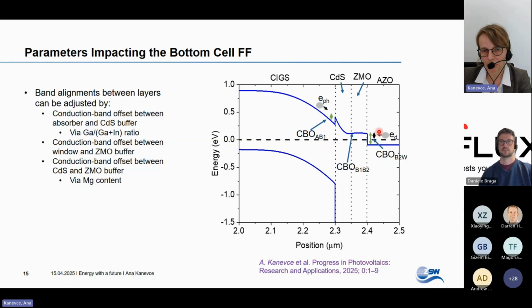So the conduction band offset can be varied. For example, zinc magnesium oxide band gap can be varied with magnesium versus zinc ratio. CIGS band gap, as said, can be varied with gallium versus indium. This is a little bit problematic because if we want to use CIGS as a bottom cell, we want to reduce the band gap. If we reduce the band gap, we pull the conduction band down and we create a larger barrier. This we have observed. Here are some examples.